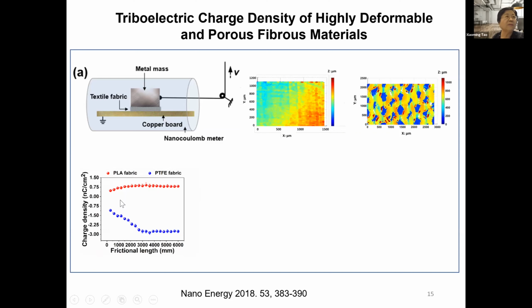The positive one is PLA, polylactic acid fiber, and the other one is PTFE. They increase the charge density, the absolute value increases, whether it's positive or negative, it doesn't matter. They increase with time and reach a certain plateau and saturation and stay there. Therefore, for these triboelectric materials, the behavior at the beginning is not constant, it hasn't reached equilibrium. Therefore, a lot of people say they use this as a sensor. I'm sorry, using it as a sensor is not that good because the system itself is changing. It's not reaching an equilibrium state.